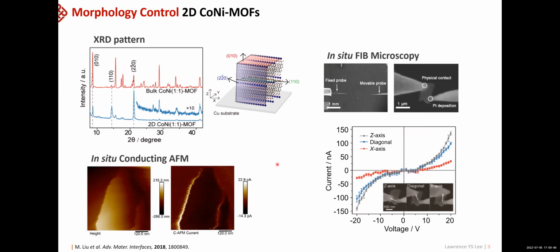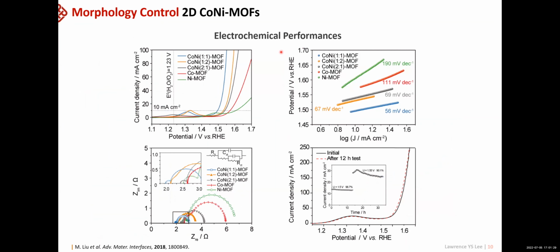Also, in the in situ focused ion beam microscopy, we first attached a single cobalt nickel MOF to the probes in three different configurations: along the Z-axis, X-axis, and diagonal. As you can see from this plot, when we connect them in the Z-axis direction, the current response is much higher than in the other configurations, which confirms that current flow has been facilitated in the Z direction. This should be beneficial because the reaction will occur on the top parts. When we measured their OER properties, the cobalt nickel one-to-one mixture showed much better performance than the single component MOF or different ratios, with better kinetics and conductivity.